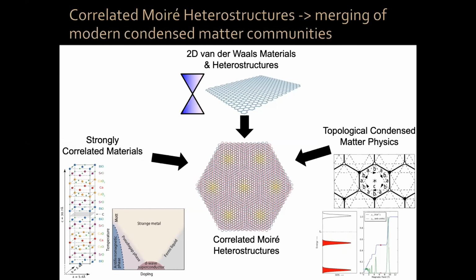Now, people are thinking about how to induce strong spin-orbit coupling in the system, right? Because it could add to the topological aspect, for example. One way that you can do that is by putting this magic angle graphene on top of an appropriate substrate. So bilayer graphene without twist angle and regular graphene both have been placed on top of, for example, transition metal dichalcogenides like WSe2 or molybdenum disulfide or tungsten disulfide. Those transition metal dichalcogenides have very large spin-orbit coupling, and people have evidence that when you put graphene or graphene systems on top of those, you are able to induce a large spin-orbit coupling in the graphene itself, okay? So several groups are trying to do this with magic angle graphene also, okay? It's sort of an obvious thing to try.